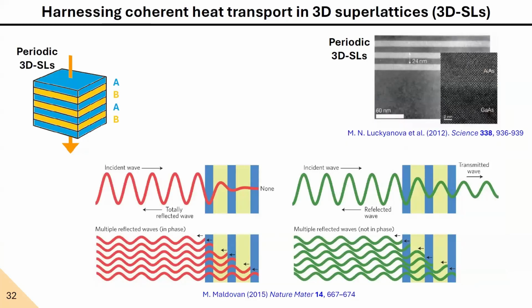So what is this coherent heat transport and how do we harness it? In 3D materials, this can be done by using periodic three-dimensional superlattices. This is two three-dimensional materials grown on top of each other in a periodic fashion. And this means that you are creating multiple interfaces, which in turn gives a reflection of all these propagating phonons at each of the interfaces. And the reflected phonons can be in phase or not in phase. If they would be in phase, they would constructively interfere in the backwards direction, meaning that no propagation can occur through our material. If the waves are not in phase, propagation can occur and our wave is transmitted.